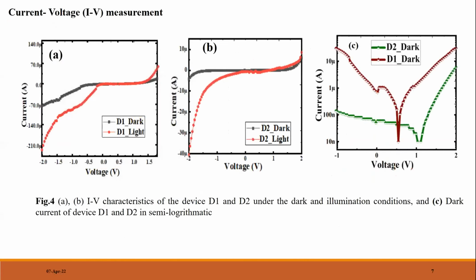Now this is my electrical characterization. I have named the devices D1 and D2, where D1 is the PTA ZnO based device and D2 is the PTA-only device. From figure A, the electrical characterization was examined by the solar simulator technique at room temperature. In dark condition, the device D1, from the PTA ZnO nanocomposite film, shows a current of around -70 microampere, and simultaneously in figure B you can see that in the dark it is nearly zero.